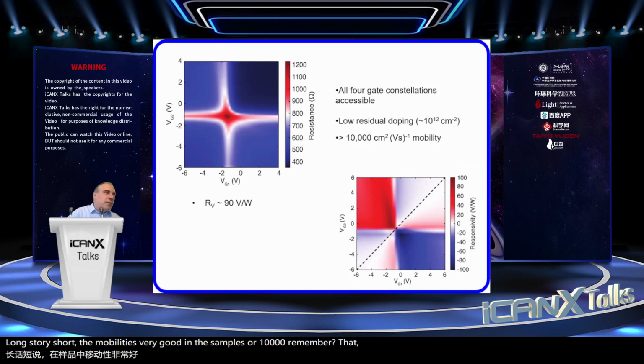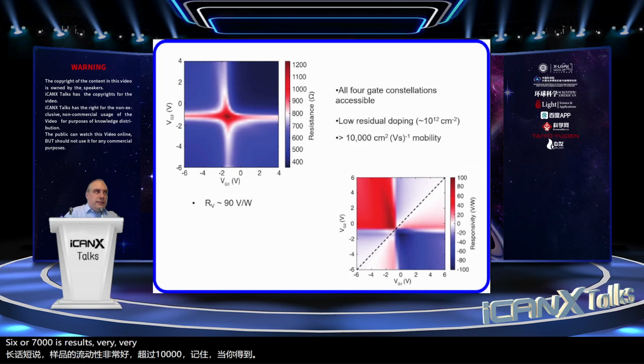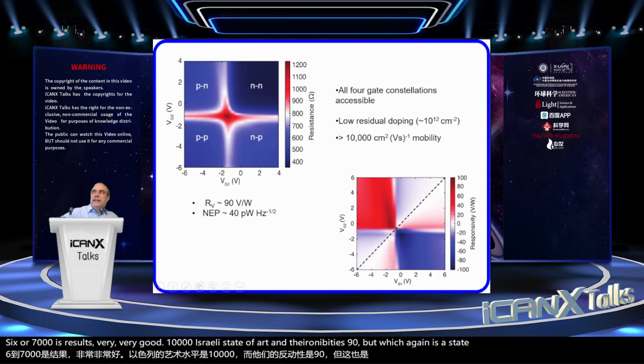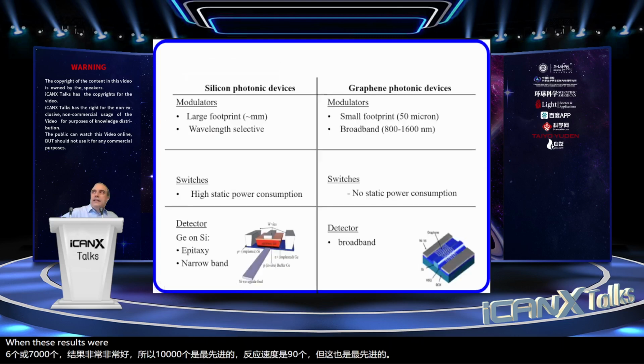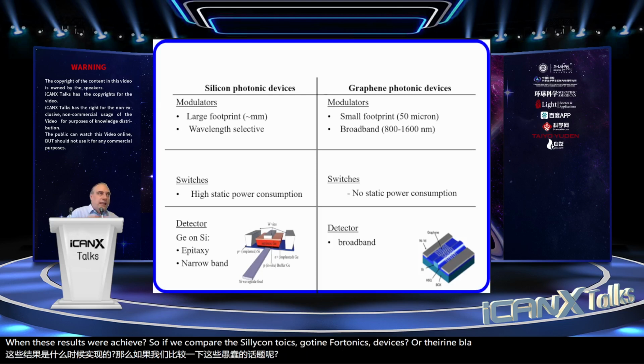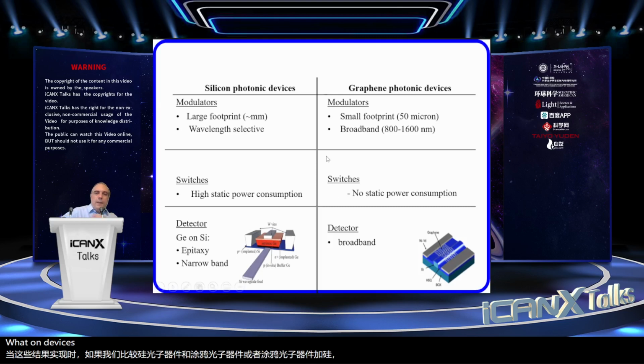Remember that already when you got 6,000 or 7,000, the results were very, very good. So 10,000 is really state of the art. And the responsivity is 90 volt per watt, which again is the state of the art when these results were achieved. So if we compare the silicon photonics with the graphene photonics devices, or graphene plus silicon photonic devices, graphene enables modulators with a smaller footprint, with a much broader band.